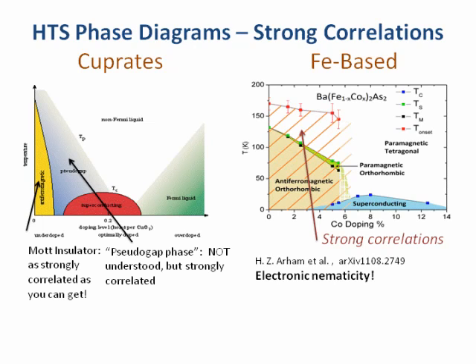This is the case of the iron-based superconductors. The parent material is barium, iron 2, arsenic 2. Cobalt has a different valence. By the way, this is all changing valences. I am being honest: in doping, I'm changing valences. It's not just substitution. If you start with barium, iron 2, arsenic 2, you're right here. This is a material that at a certain temperature, about 135, up here is paramagnetic and tetragonal. Below here is antiferromagnetic and orthorhombic, no superconductor. Now you start putting cobalt in here, and the cobalt replaces the iron in this case and creates positive holes. As you add, all of a sudden you start getting some superconductivity, and you keep adding. If you overdose here, then it becomes a fairly normal liquid again.